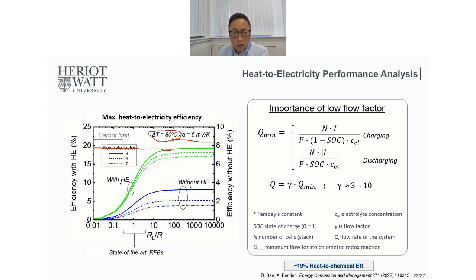Under this assumption, the Carnot limit is almost 23%, and there is a very small gap between the 2 efficiencies. Of course, this is the ideal case, but for the first time we suggested what the theoretical limit is, considering the practical working condition of this type of flow cell. So the important message here: if we use a poor heat exchanger, HE stands for the heat exchanger, then we can only have between 2 to 3%.